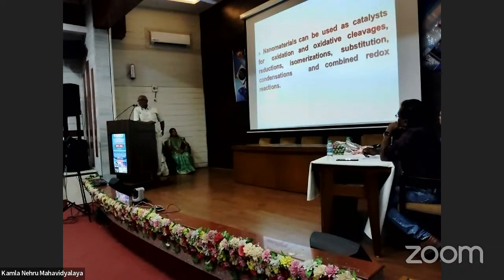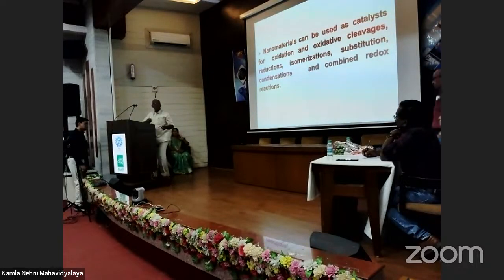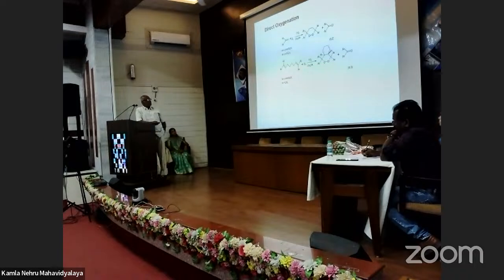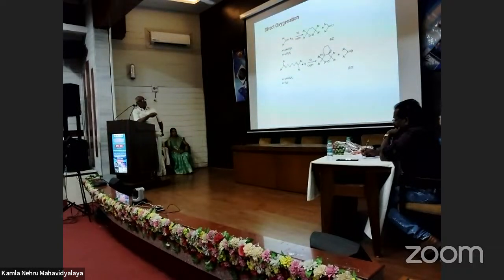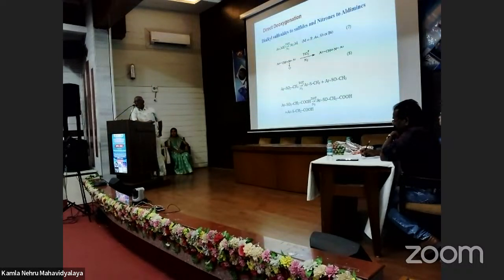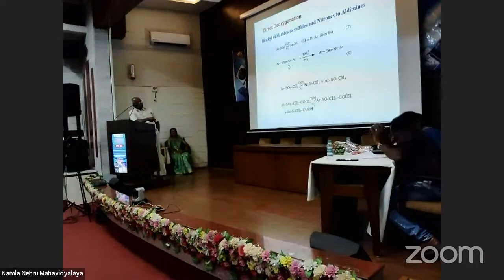So what we are going to see are some of these reactions, with some examples taken from the literature. The nanomaterial can be used as a catalyst for oxidation or oxidative reduction, substitution and combined redox reactions. So this is a direct oxygenation. They used only TiO2 with acetonitrile solvent, and they are getting this ketone. That is the formation of this ketone, an oxidation reaction. Similarly, you can have deoxidation reactions, such as sulfoxide to sulfides or nitrones to amines. You can see the nitrones forming the amines, and similarly sulfoxide is forming the sulfides. So all these are deoxidation reactions.